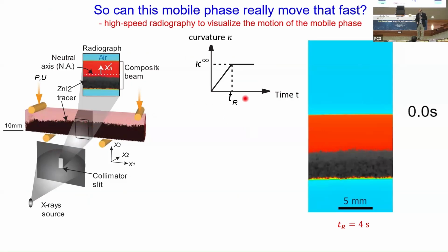This is a 4-point bend experiment. The blue is air, the red is pure silicone rubber, the black down here has the zinc iodide, and the blue here again is air. This whole thing is going to move up as we do this 4-point bend experiment. And what you will see here is that this black front moves nearly 5 millimeters in 4 seconds, basically.